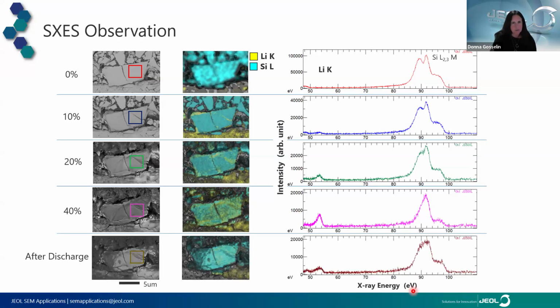And finally, I just want to show an example of the fully discharged system. Here the peak shape has changed fairly dramatically, and the lithium intensity has decreased. We still see a little bit of lithium left in the particle. It hasn't all gone away. But this peak shape has changed. It looks more like the spectrum of amorphous silicon versus crystalline silicon.